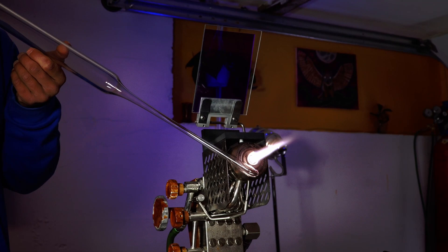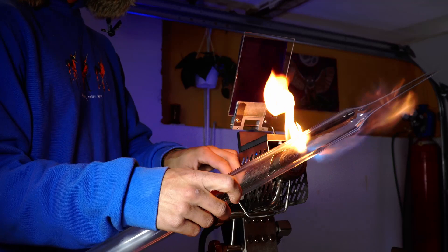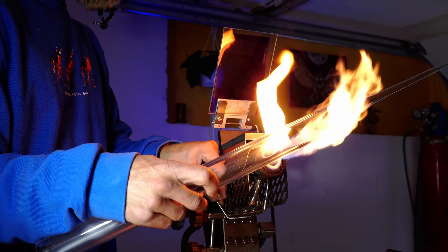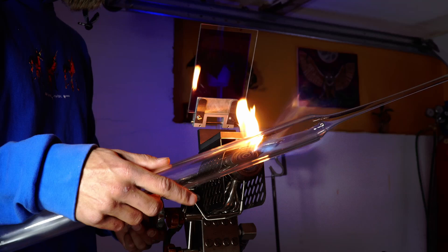So now I've just made myself a good annealing flame. An annealing flame on this torch uses compressed air and propane, but on many torches you can just use oxygen and propane. This is a type of flame you're going to want to preheat your glass. You can also use this flame throughout the process to anneal it, get rid of some of the stress and make it more viable for working. Less likely to shatter.